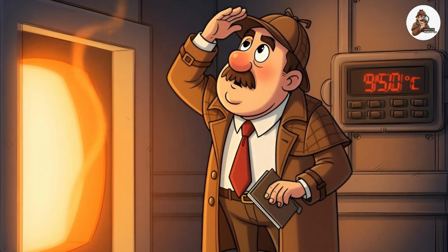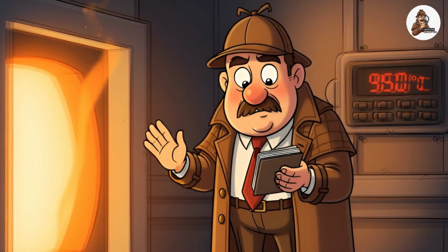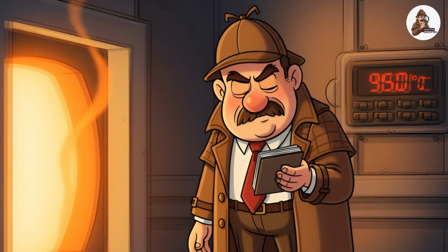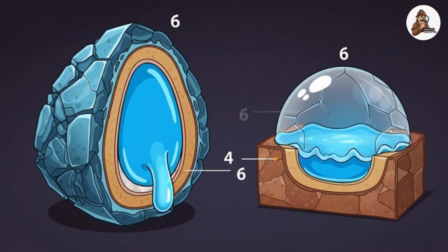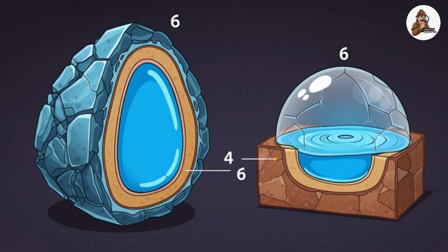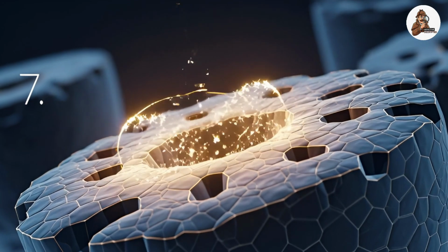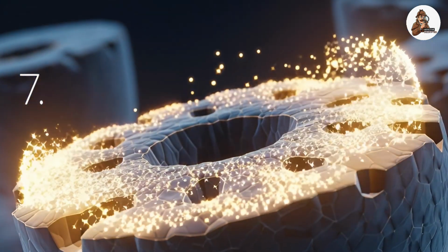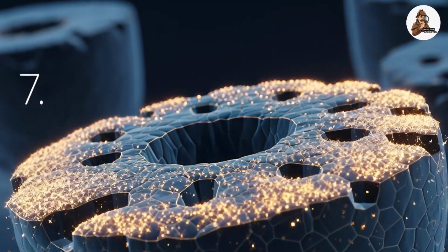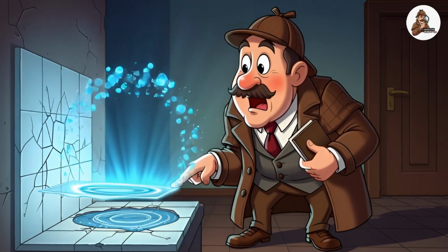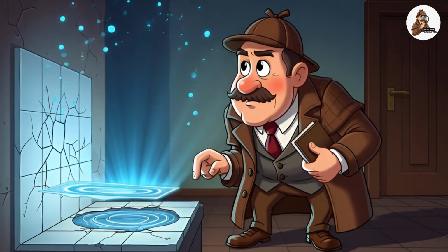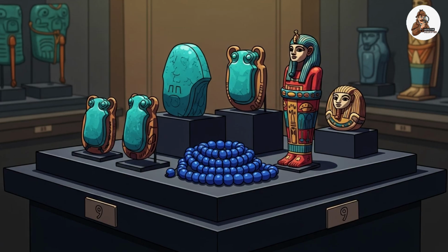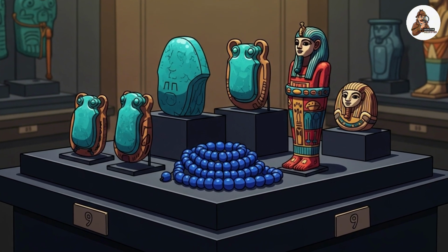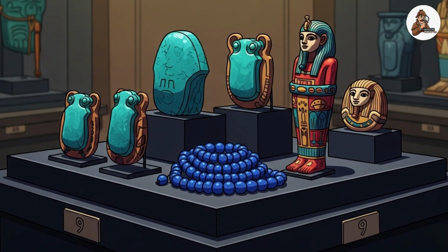When fired at temperatures between roughly 800 and 950 degrees C, the material behaves in a way that still challenges modern replication. Instead of requiring an applied glaze, faience generates a vitreous coating from within. As heat rises, alkali salts migrate outward through the porous quartz body. At the surface, they interact with copper compounds and silica, forming a thin glass layer rich in copper silicates. This self-glazing process produces the intense turquoise and deep blue tones seen on beads, tiles, and figurines spanning more than 3 millennia of Egyptian history.